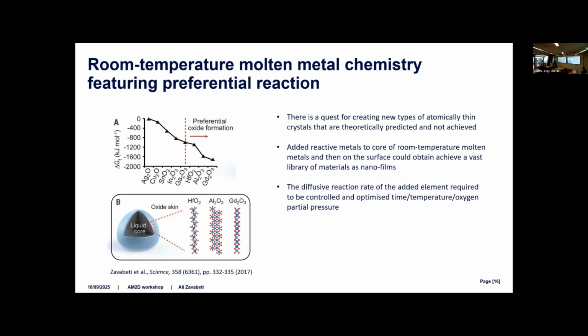The reason for that is we need to allow enough diffusion for the large atoms, gadolinium and hafnium, to diffuse to the surface and react with oxygen. So here we had less than 1,000 ppm oxygen and sufficient time to get very pure oxides. But again, liquid metals give us a unique chemistry where we can harvest a large portion of the table of elements in 2D.